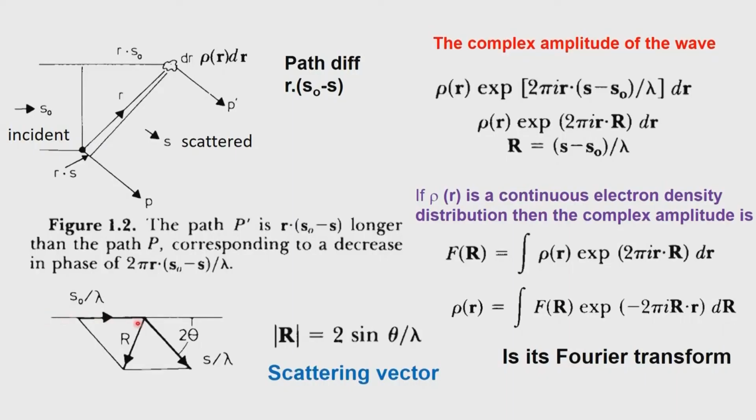So, we have the generated X-rays, with a certain wavelength lambda. All this discussion came up because I was using this lambda as a normalization factor. In most of these experiments we try to get the lambda to be a single value. In the earlier experiments which Laue and others did, which we are going to discuss now, they used white radiation. However, it is now recommended that we use monochromatic X-rays, a single wavelength X-ray. So the incident beam is normalized with respect to that.